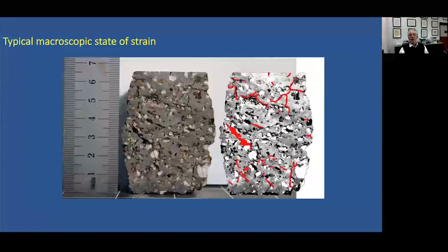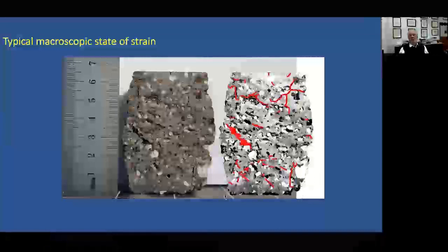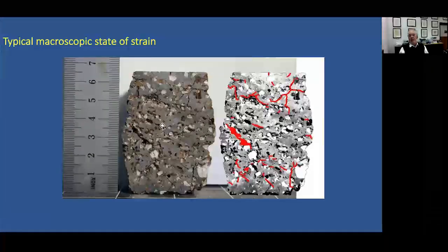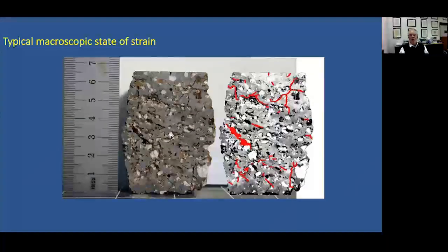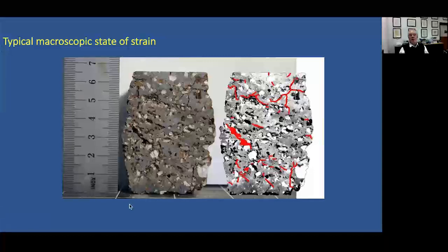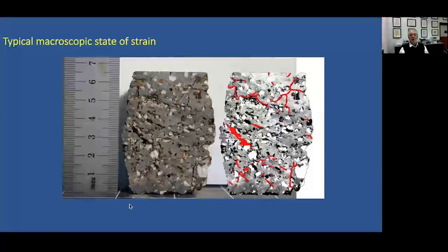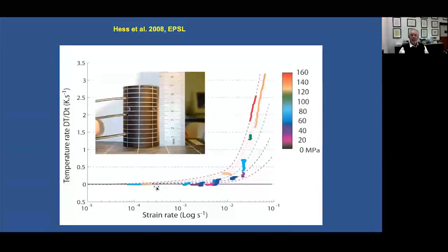Here we see beautifully this barreling deformation of an unsupported sample at one bar. You can see the crystals in it. You can see the thermocouple, which is poking through here. You can see the size of the samples, quite substantial samples, about the size of my fist. And what you can also see is that the temperature increases as we increase the strain rate.